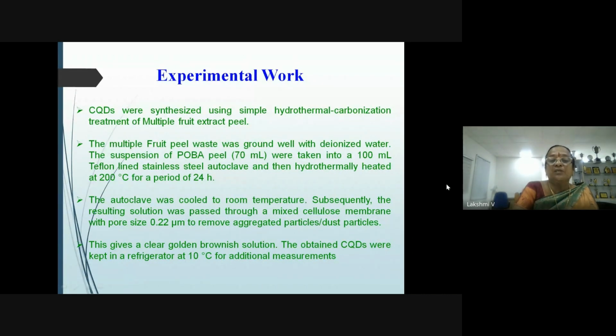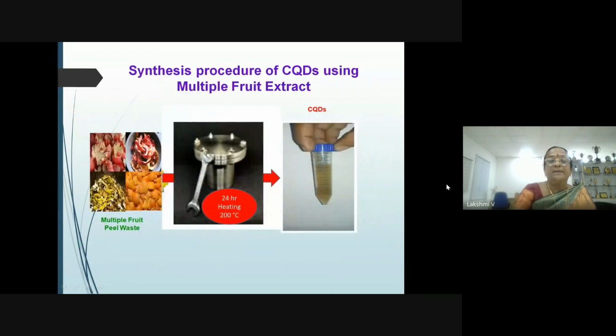Subsequently, the resulting solution was passed through a mixed cellulose membrane with pore size of 0.22 micrometers to remove aggregated particles or dust particles. This gives a clear golden brownish solution. The obtained CQDs were kept in a refrigerator at 10 degrees for additional measurements. This is the multiple fruit peel waste, which I have taken the photo of, and the multiple fruit extract after 24 hours heating at 200 degrees Celsius, and we have got a golden brown color solution, which we believed to contain CQDs.